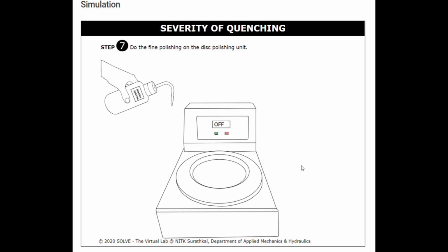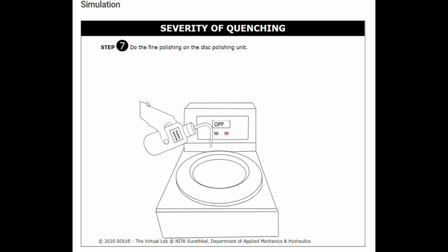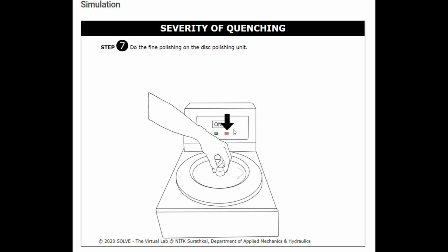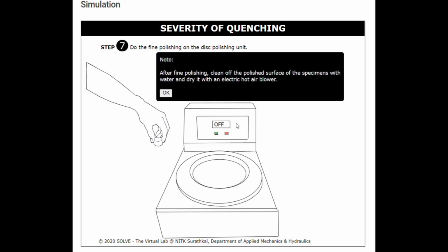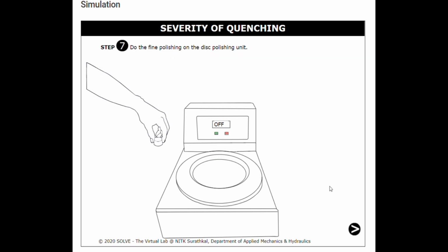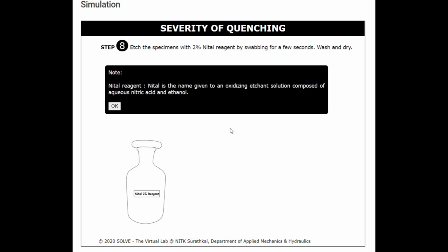Now we do the fine polishing on a disc polishing unit. After fine polishing, we have to clean off the polished surface of the specimens with water and dry it with an electric hot air blower. In step 8, we etch each specimen with 2% nital reagent by swabbing for a few seconds. Then we have to wash and dry it.